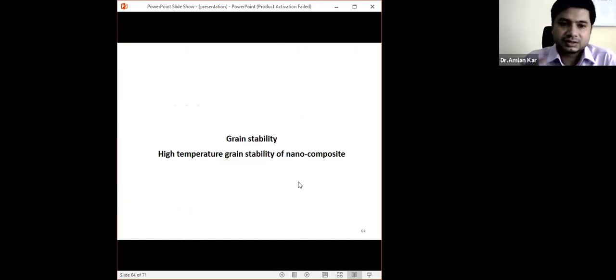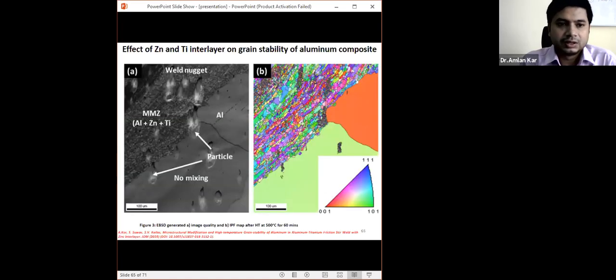Now I'm moving to the grain stability of the composite we have developed. The composite is subjected to high temperature at 500 degrees centigrade for 40 minutes. This is the location of the composite or the nugget zone, and this is the outside zone. From there you can understand that where the particles are distributed very nicely, the grains are not subjected to grain growth. Because the particles are sitting at the grain boundary and pinning the grain boundary, which is very important for grain boundary mobility or grain growth. So the particles hinder the grain boundary mobility, and therefore we obtain very good grain stability.